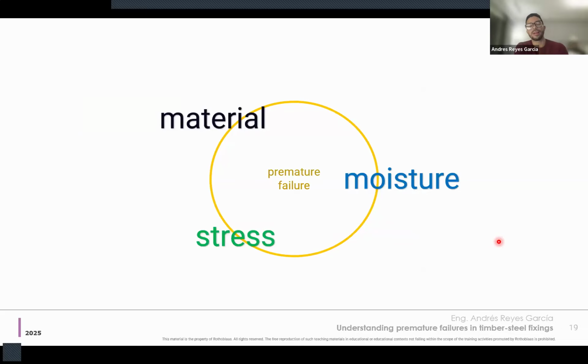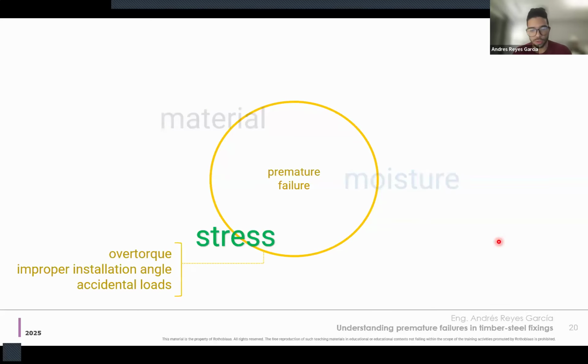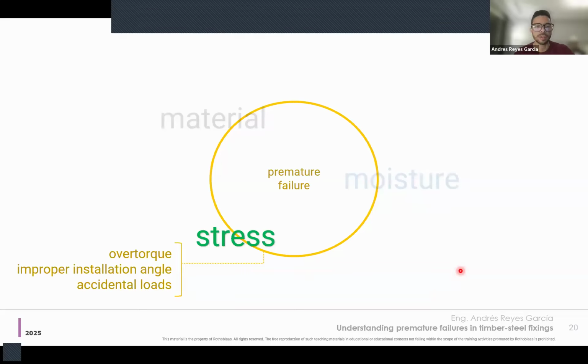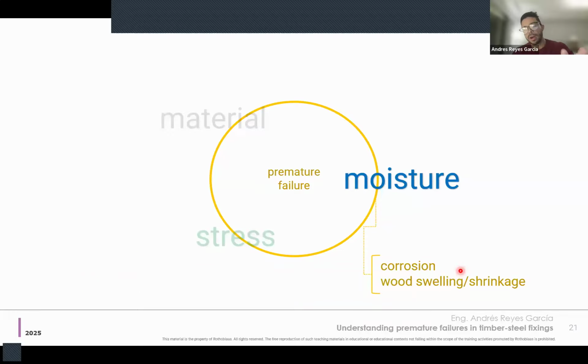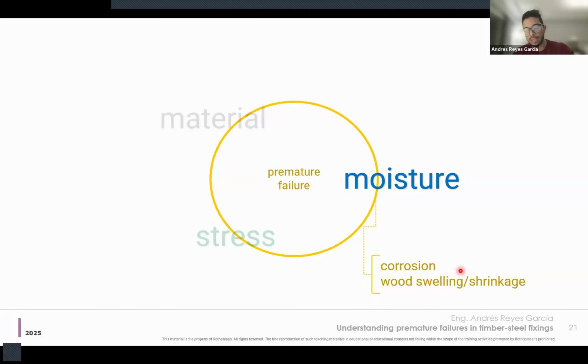Back to the main factors that lead to premature failure. There are these three: material, stress, and moisture. How is the stress factor? It can be over torque, improper installation angle, or accidental loads. These can lead to failure even without any material susceptibility or any presence of moisture. Also, moisture can lead to failure due to corrosion or wood swelling. Mostly corrosion will induce hydrogen absorption, and this is what we will focus on. Moisture would lead to wood swelling or shrinkage that becomes a stressor, so it's not moisture itself that leads to failure.